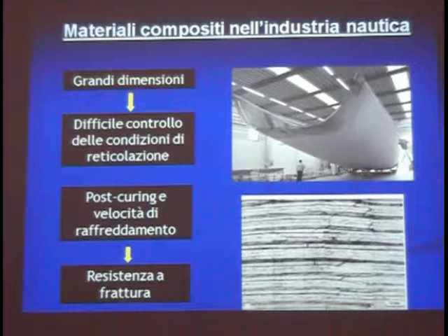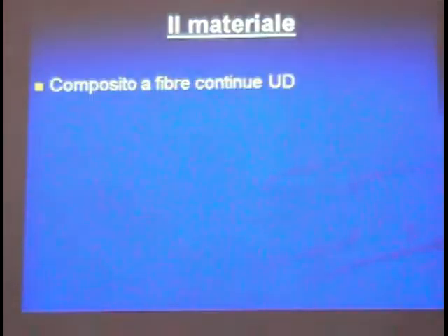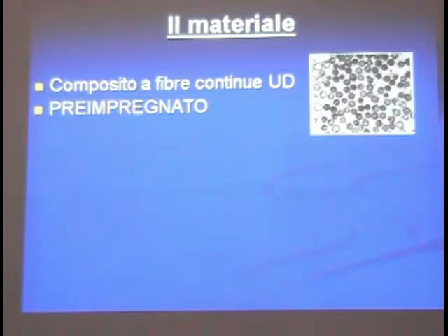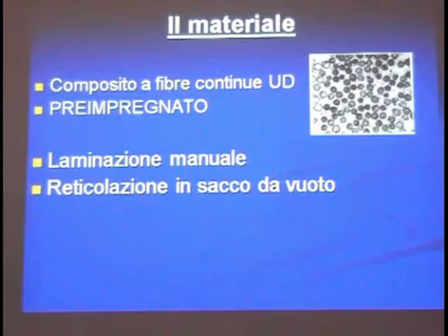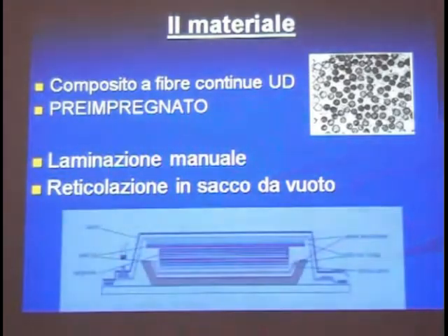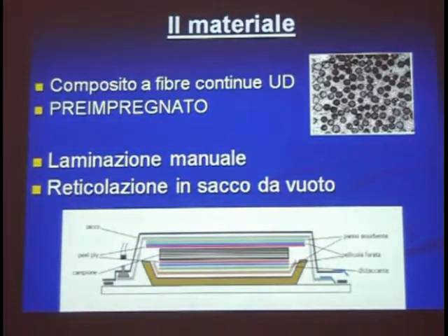And then we have been studying the post-curing and cooling rate effects on the fracture resistance of laminates made of continuous fibers, unidirectional, and epoxy resin matrix. This is a so-called pre-preg, in which the resin is already present together with the fiber. Then samples have been stacked up using a manual lamination procedure, and then the material has been cured in a vacuum bag arrangement, which is shown in the picture.